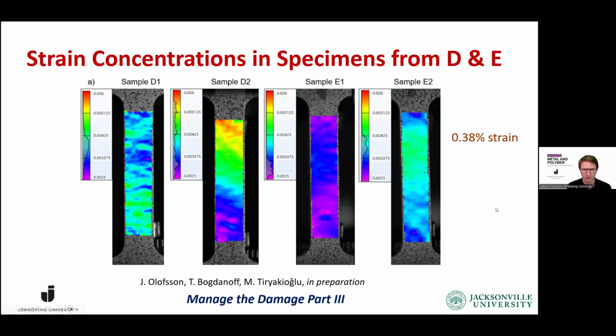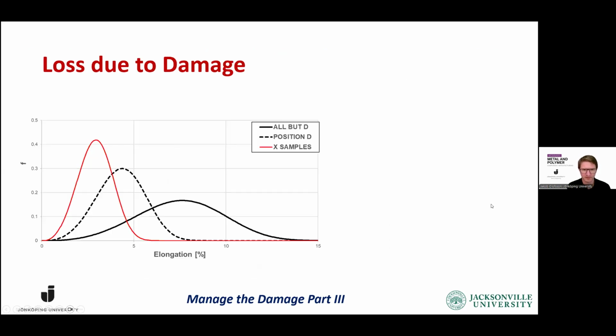So that really explains why this position D comes out as different. And if we proceed to the next slide, we know that the elongation values here are expected to follow a statistical distribution. Then we can fit the parameters of a Weibull distribution to these samples and plot these Weibull distributions. And that is what you see here.